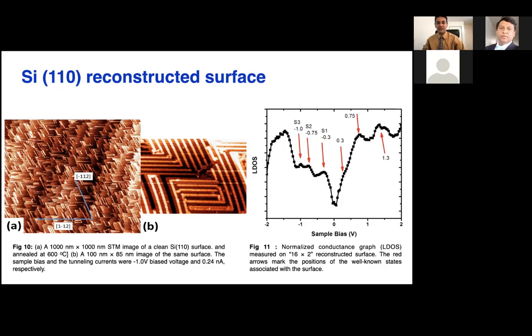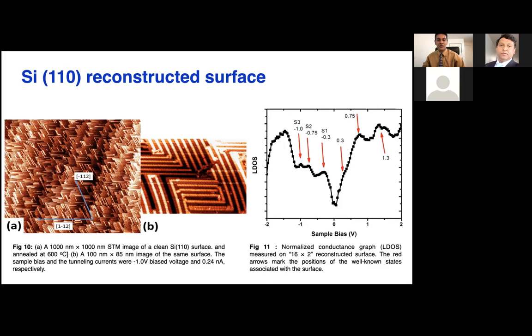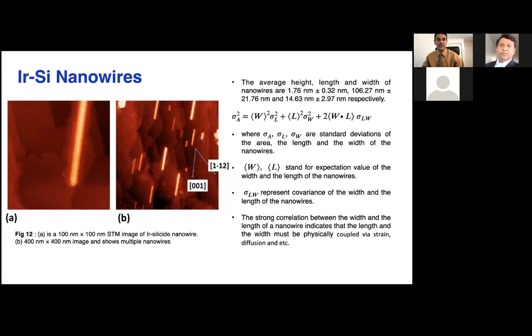Below the Fermi level, there are another two surface states, S2 and S3, that can be attributed to the step edges on the surface. And above the Fermi level, there are three different surface states. Those surface states can also be attributed to the pentagon structure of the silicon 110 surface. Okay, now that is all for the cleaning part of the silicon 110.